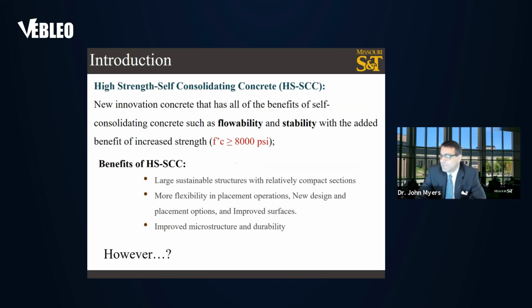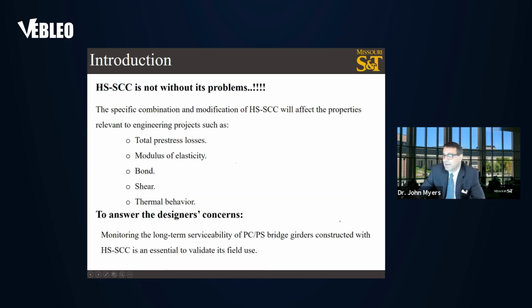This is a new innovative concrete that has all the benefits of SCC, as we've talked about, the flowability, the stability, with the added benefit of strength. So the strength is equal to or greater than 8,000. And this helps to have more compact sections. This helps us in terms of efficiency of production. And this can also improve the microstructure and durability.